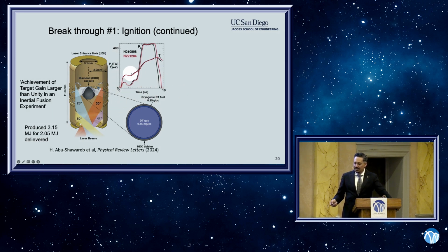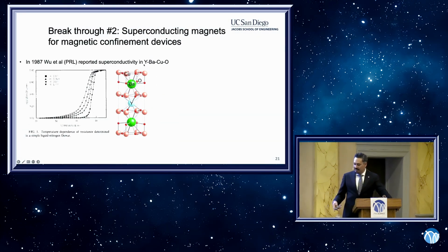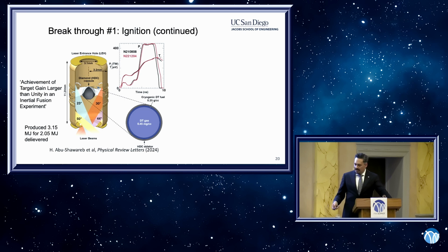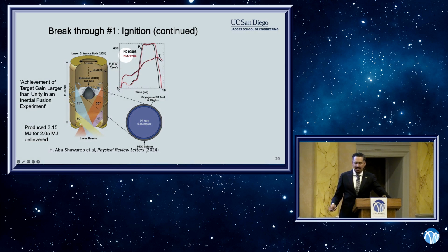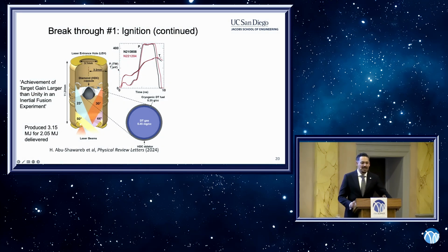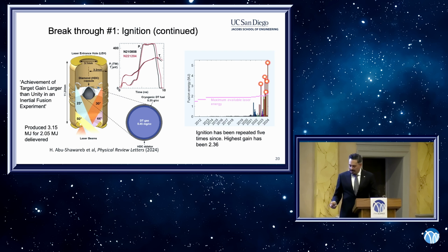This curve here marked P is the laser power. You can see the laser power increases, and what follows is a temperature increase. Now that temperature increase is huge, and you see the temperature that was recorded during the shot is here in the hundreds of eV, right? So that's millions of degrees Celsius. Very, very hot. Importantly, this has now been repeated 5 times.